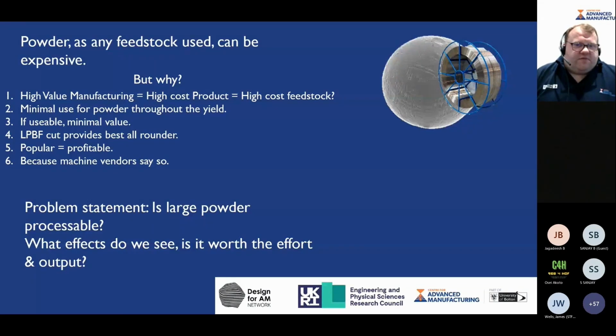We'll hear much more on feedstock tomorrow, but when we're atomizing powder, the yield which is of the highest value for us in laser powder bed fusion is minimal. Beyond that sweet spot, that laser powder bed cut, it's not always usable if it's a new or relatively niche material, like a scalmalloy, for example. There's not lots of use for the other sizes that are natural as part of the atomization process. So the laser powder bed cut gives us a best all-rounder, and it's popular because people want it, and people want it because the machine vendors tell us that's the powder to use, and that makes it expensive.